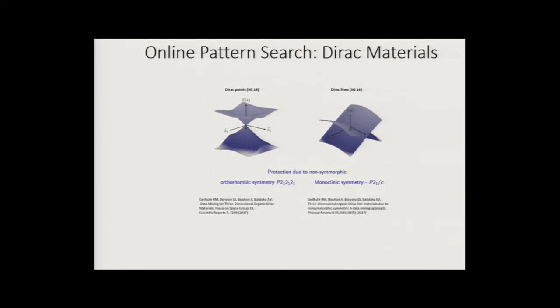So let me just quickly go through. We do find organic materials. Looking at this massive amount of band structure outcomes, for instance, space group 14 universally returns Dirac points. There are plenty of non-symmorphic groups like 14, 19, and others that, just like in the hard inorganic materials, return Dirac crossing points. Those are Dirac crossing points, not Weyl points, because there is no spin-orbit coupling. Okay?